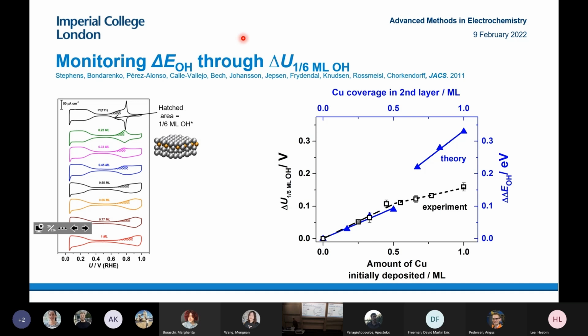When we did these measurements in the surface alloy, we were hoping to get what we got, but we didn't actually know. So they did the DFT calculations before we did the experiments, and we were saying, oh, if we get a surface which showed a voltammetric shift of 0.1 volts, that's what we expect to see, the maximum activity, and that's what we got. So we were really excited when we got this data.